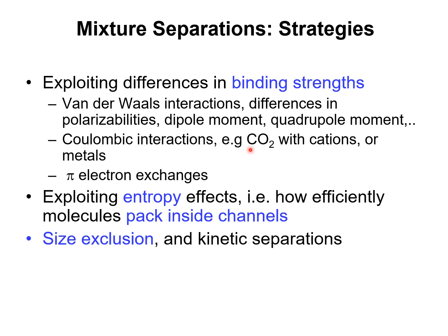For example, CO2 experiences Coulombic interactions with extra-framework cations of zeolites or unsaturated metal sites in metal organic frameworks, and pi electron exchanges between guest molecules and the framework atoms.